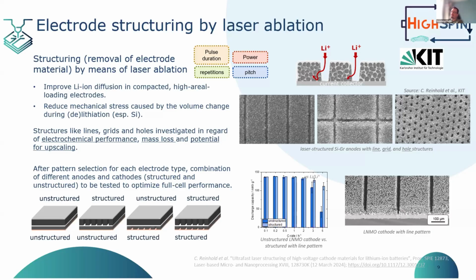And then, of course, these different electrodes are assembled into cells and tested for electrochemical performance and potential for upscaling. One thing that has to be considered is that because we're removing material, we have a mass loss here. That means we're removing from the energy density of the electrode, so that needs to be kept in consideration.